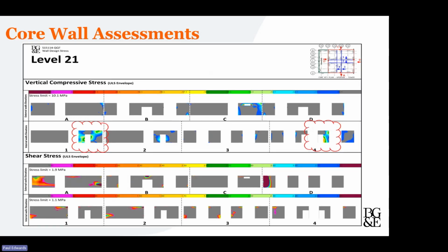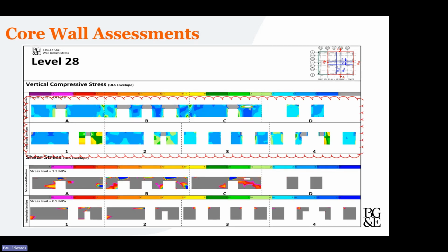Again, certain areas, level 21, the areas in red cloud are where an intervention is required rather than it being acceptable or on the verge of acceptability. And then you get up to levels 27, 28, where in effect, for some reason, the whole core wall is not performing well.